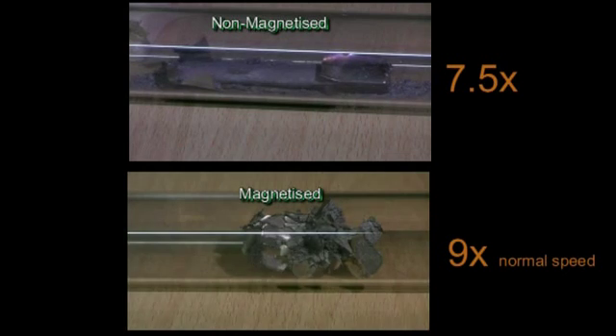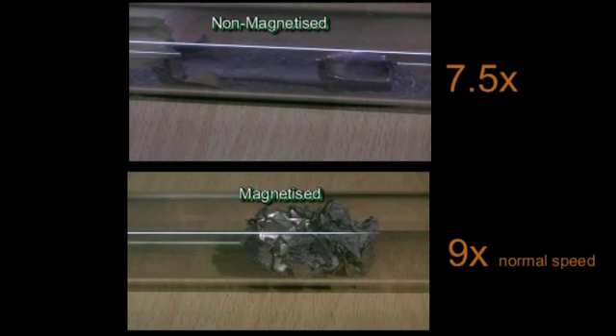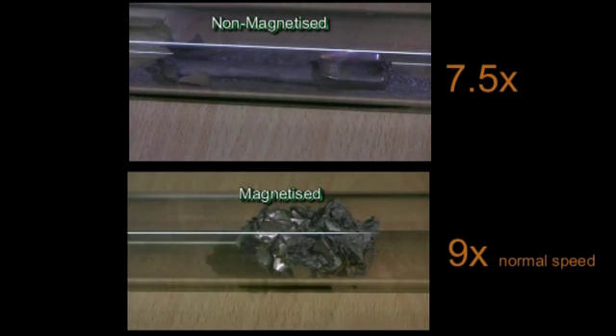This is causing the formation of a metal hydride and a corresponding volume increase. As this material is not very ductile, this volume increase is causing the material to fracture into smaller pieces.